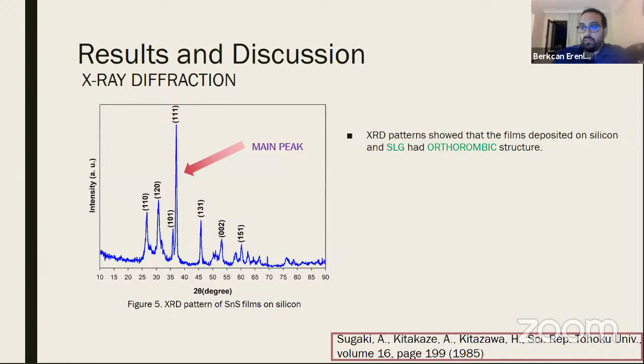There are more peaks in the film deposited on silicon, as you can see in figure 5, because soda lime glass is amorphous and silicon is crystalline. All the tin sulfide thin films showed 111 plane preferred orientation and orthorhombic crystal structure.